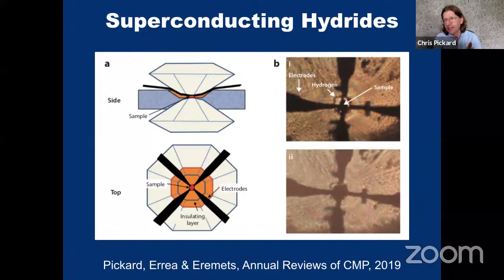But the key thing is to be able to measure the transport properties. And so you have to be able to put these electrodes into your sample and make contact with your sample. These are 4-point electrodes. You need to make sure that they're appropriately insulated from each other, and that they maintain their integrity when you squeeze these diamonds against each other. And frankly, I have no idea how they manage this, but they do. I'm pretty sure it doesn't work every time they try it.